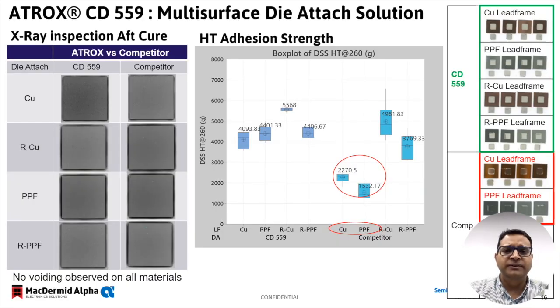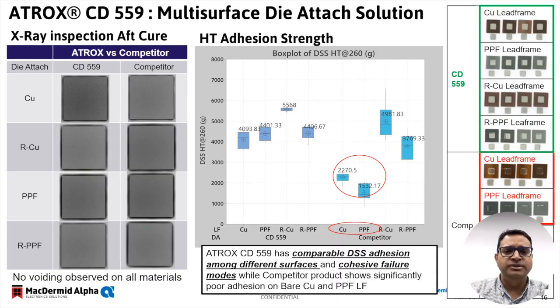Another noticeable difference can be seen in the failure modes. The failure modes indicate how the material has failed when the die has been sheared from the substrate. CD559 demonstrates a cohesive failure mode, which indicates good adhesion to both the die and lead frame surfaces that it is attached to. Whereas the competitive material shows an adhesive failure mode on non-roughened surfaces, again indicating preferential adhesion to one surface over the other, which can have implications during the reliability testing.